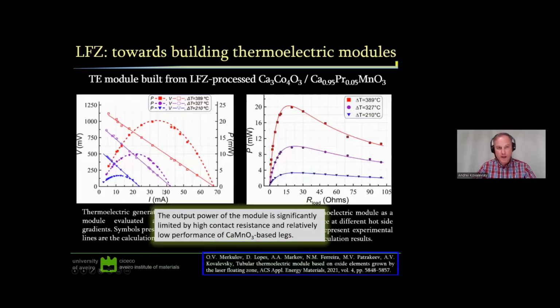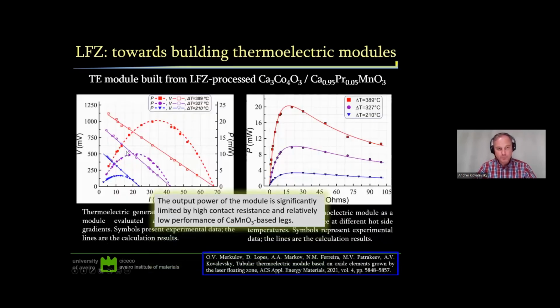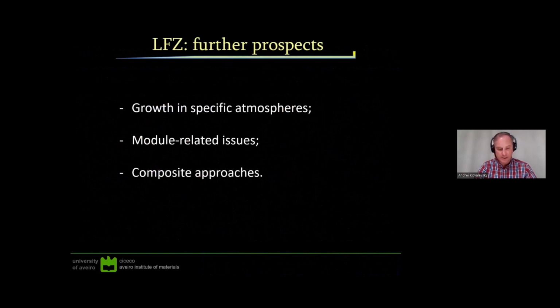Here I put some results on our current voltage characteristics and also power of this module. We compare this performance with the oxide-based modules from the literature. We didn't achieve something outstanding here, but mostly it was not because of the module design. It was because the output power was basically limited by those calcium manganite-based legs, which had performance less than expected. We are now trying to integrate other materials, and we still think this approach can result in very interesting results.